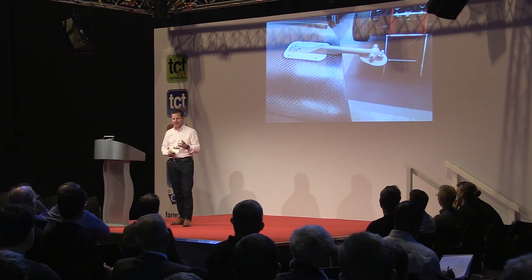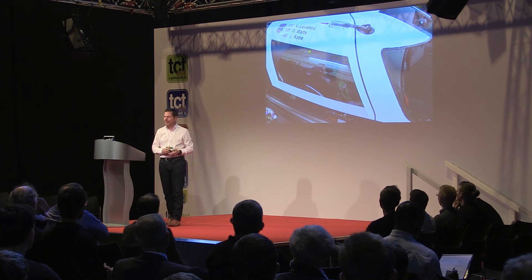When we weighed up CNC machining in steel versus 3D printing using metal laser sintering, we couldn't even source the billet material in the same time it would have taken to print the part. By printing it via metal laser sintering in titanium — the most readily available material for that process — we actually got a part that was cheaper, lighter, and stiffer than we could have made through our previous processes. That doesn't work across the board, but in this application making two car sets of parts, it worked and gave us real benefits. There's the component fitted onto the race car.